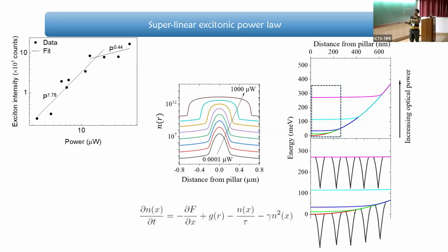And if you do the calculation, it turns out that it just becomes flatter and flatter. So the diameter of the pillar is actually increasing just with power. It's a dynamic variation of the pillar diameter in some way, right? However, you don't see this blue shift, because I told you that there is this electron doping, which is kind of red shifting, and just cancelling each other. But nonetheless, the pillar diameter is actually increasing, and so you are actually covering more and more Moiré pockets. It is an area, right? It will go as a square, and that's why this close to 2 is coming.